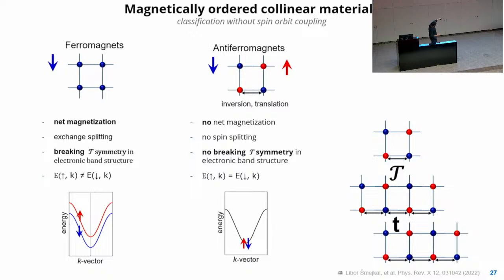So you see now we have again red on the bottom, blue on the top, as it was in the beginning. So this means that in this system, time reversal symmetry together with translation is a symmetry property of the crystal. And in the band structure, this means we have no time reversal symmetry breaking. In the band structure, this is something you have to know: the translations, they don't matter, so we can just ignore them. So this means time reversal symmetry is a property of the system. And that means, since time reversal symmetry changes spin up to spin down, we have to have the same bands for both of these states. And that means it's boring. Or that's why we have problems to actually have spintronics applications for these materials, because spin up and spin down electrons follow the same states. So we cannot have these spin polarized currents in these systems.